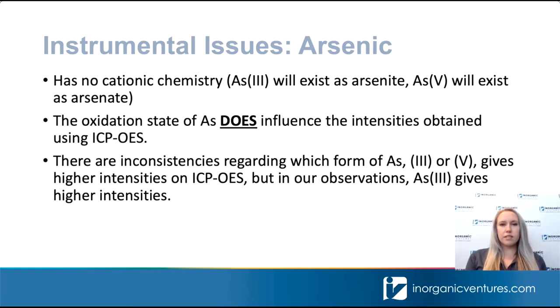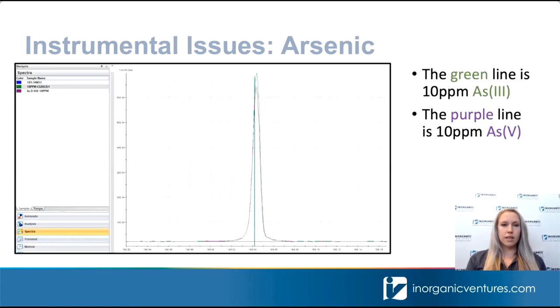There is some inconsistency about which arsenic species gives a higher intensity, but in our analyses, we have seen that arsenic 3 actually gives higher intensities than arsenic 5. This is an example of some results we obtained from an analysis on 10 ppm arsenic 3 and 10 ppm arsenic 5 standards on our ICP-OES. As you can see, the green line is arsenic 3 and the purple line is arsenic 5. Arsenic 3 has consistently given us about a 3-6% higher intensity than arsenic 5 when running on ICP-OES.